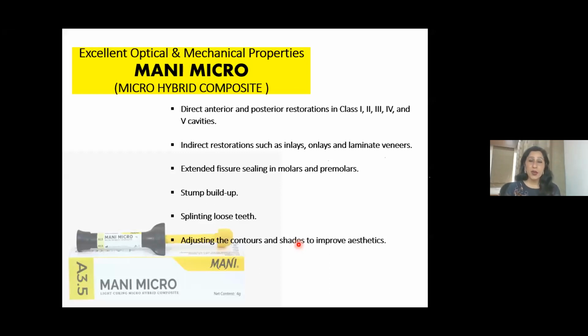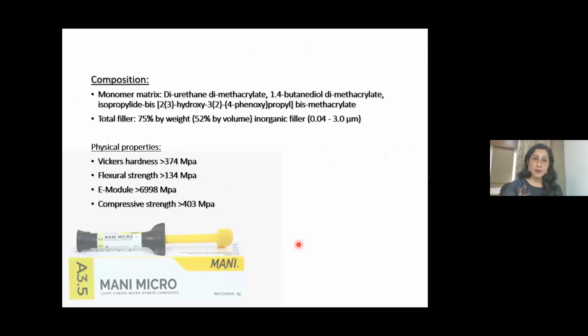So Mani Micro is a great microhybrid composite. It can be used both in direct anterior and posterior restorations, so your inventory is less. It can be used in indirect restorations such as inlays, onlays, and laminate veneers also, because it has very good strength. It can also be used in fissure sealings in molars and premolars, can also do stump buildups and splint loose teeth, adjust the contours and shades to improve aesthetics. So it can do almost all the things that are required in your oral cavity with composites, and it also has a very good compressive strength, that is 403 MPa.